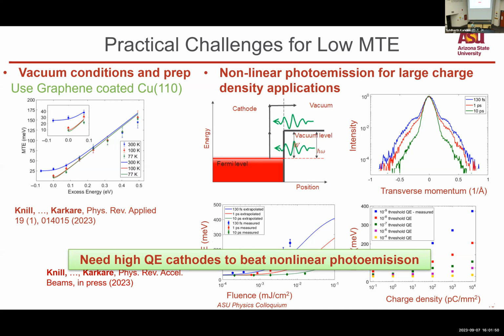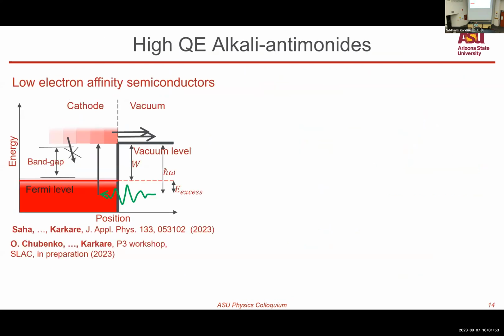Well, turns out we have high quantum efficiency cathodes. There's a whole family of low electron affinity semiconducting materials, which are often used as cathodes. Alkali antimonides is a subfamily in this group. In these materials, there's some very interesting photoemission physics going on. Electrons are excited. In these materials, the band gap is very comparable to the vacuum level or to the work function. And electrons are excited into the conduction band from the valence band via light. And these electrons cannot relax back here because there are no states to relax into.